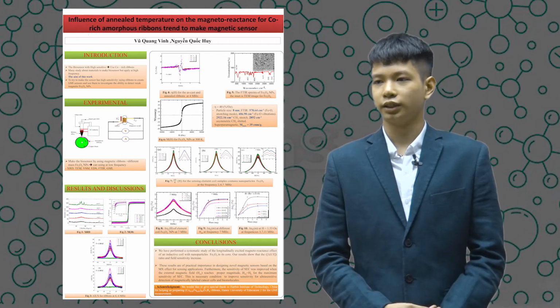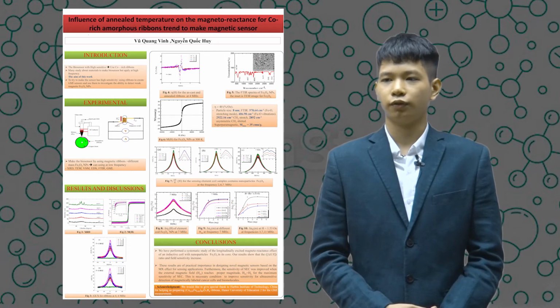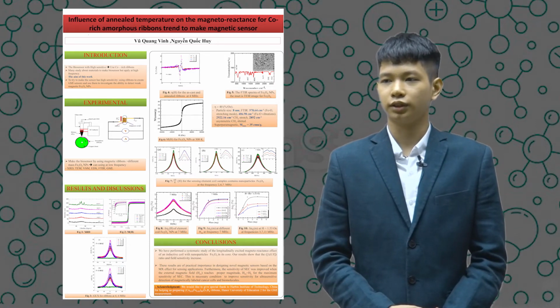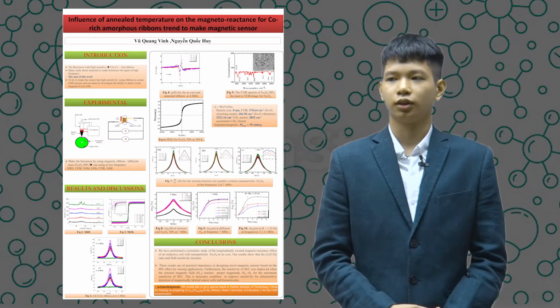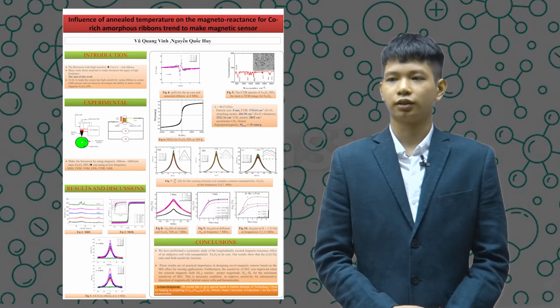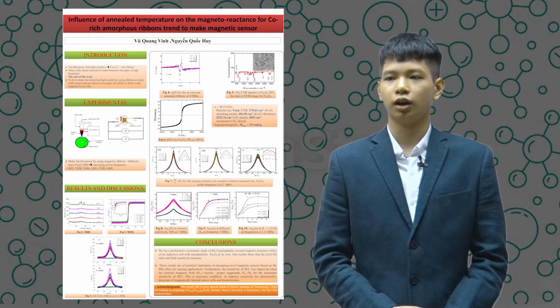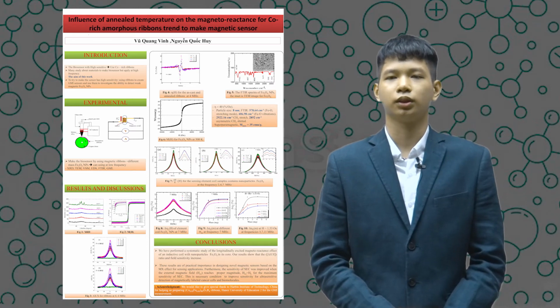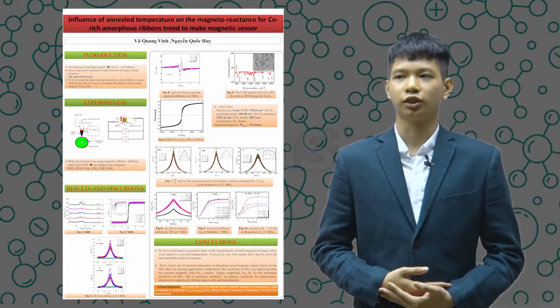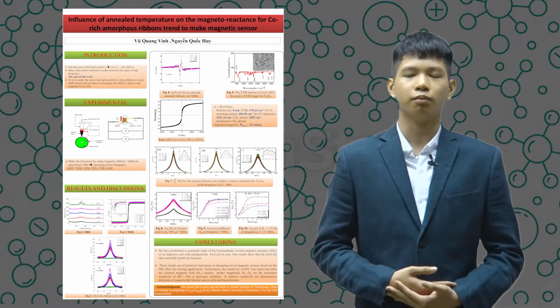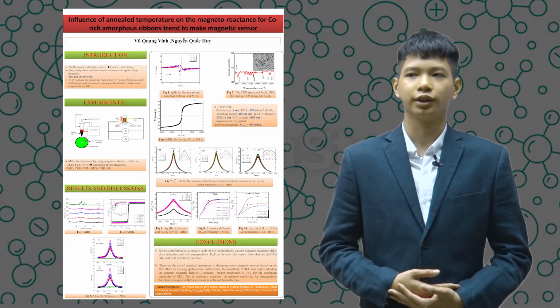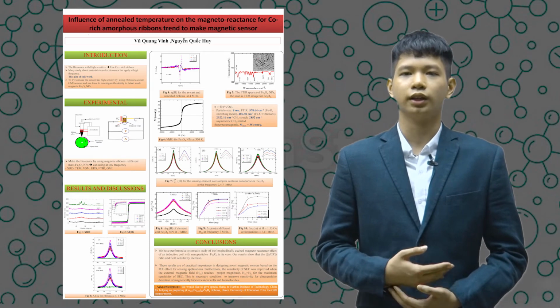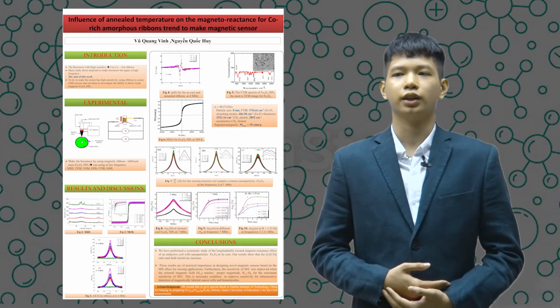Fig 4: delta X per X for the as-quenched and annealed ribbons at 4 MHz. The field sensitivity of delta X per X as a function of DC magnetic field for the as-quenched and annealed ribbons at f equals 4 MHz. The ribbon annealed at 300 has the highest sensitivity value, about 40% per Oe. We found the optimal condition for the CoFeZrB compound at TA equals 300 degrees C, with the highest value of delta X per X and field sensitivity of delta X per X.